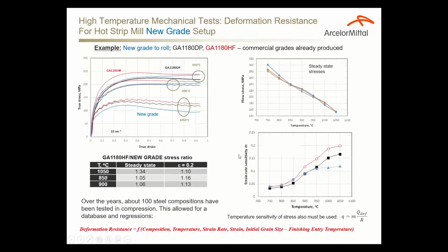This procedure is also being used to set up the strip rolling of a new grade. Again, using the sensitivity parameter and obtaining the stress ratio. So it means we give the mill numerical, quantitative information of how much harder or easier the new grade is to roll compared to the grades that they are already producing.